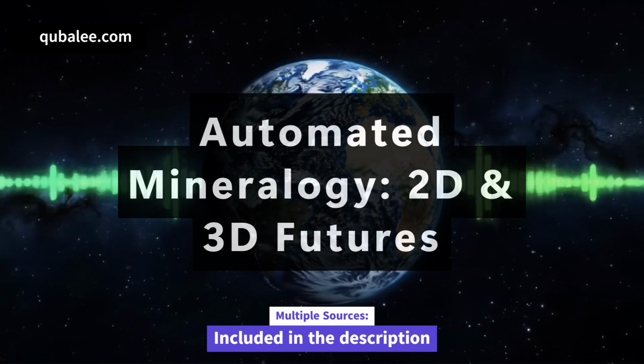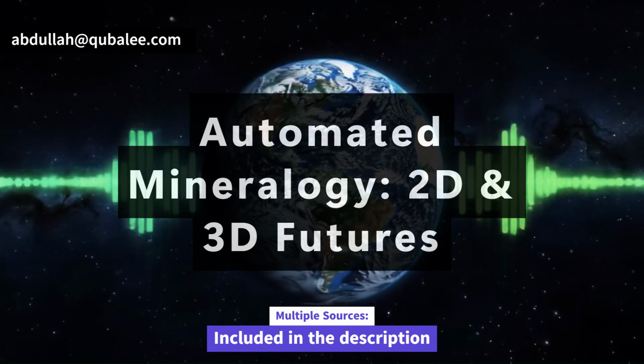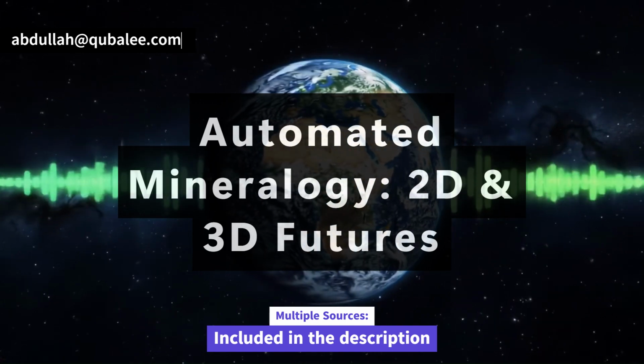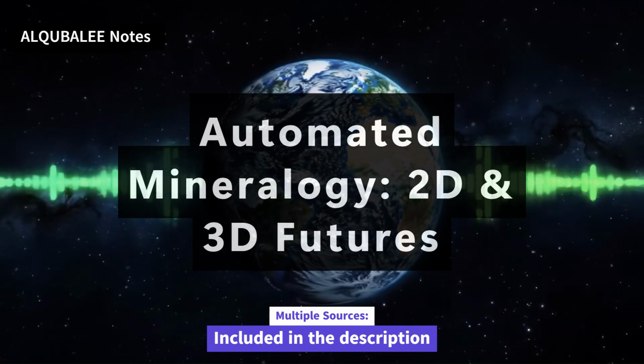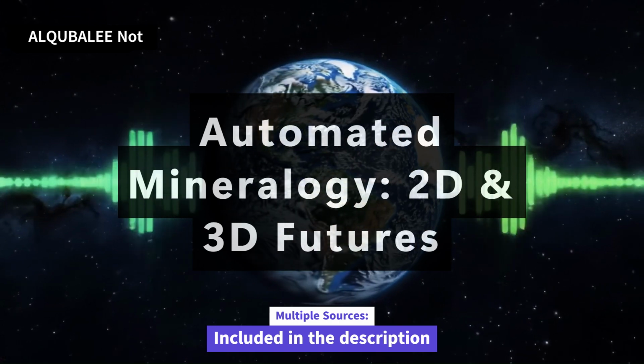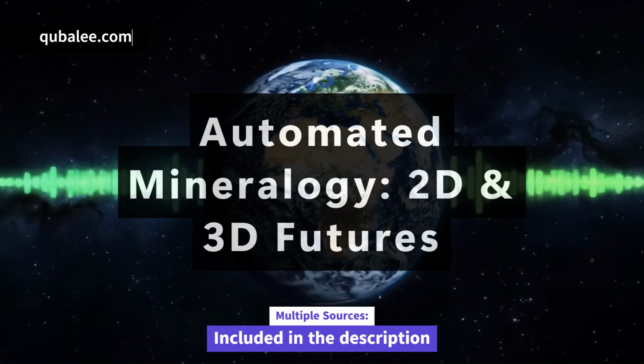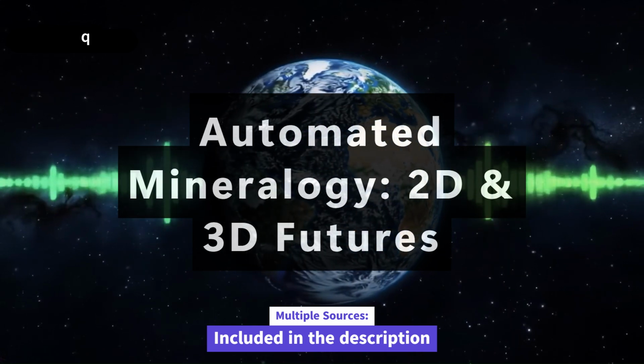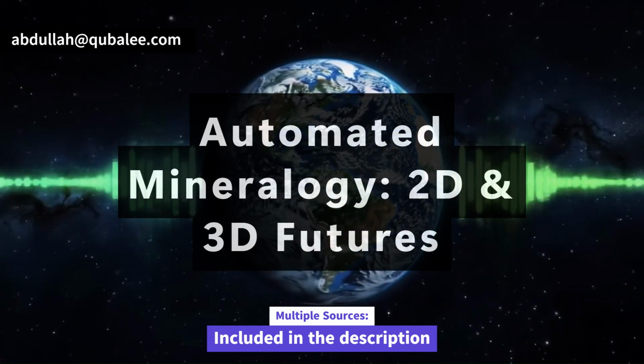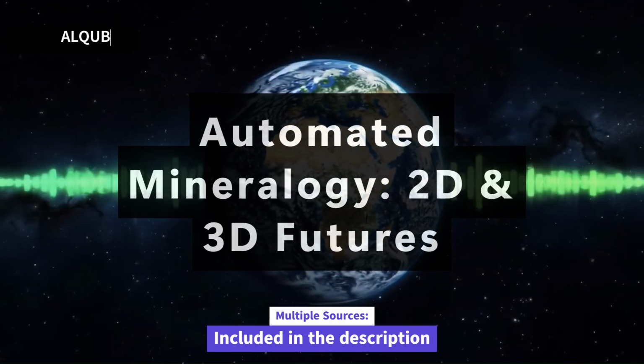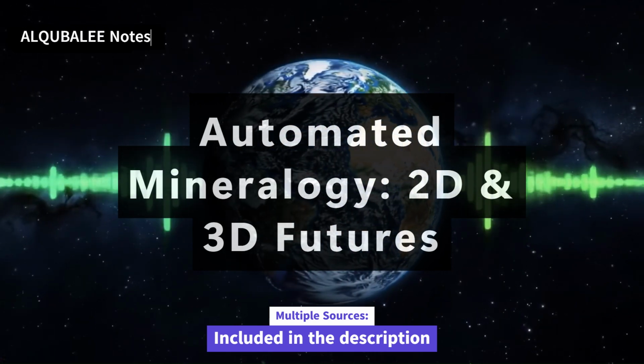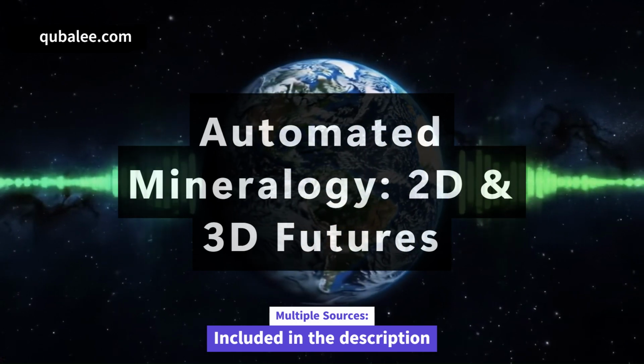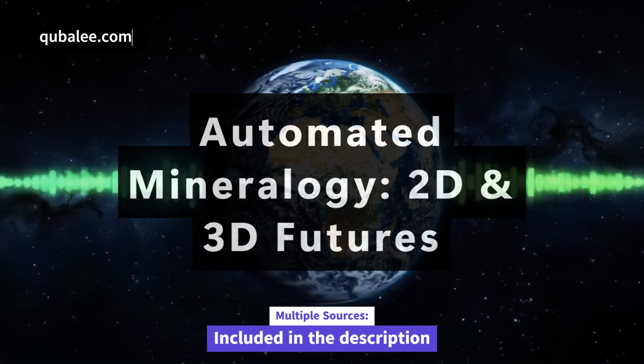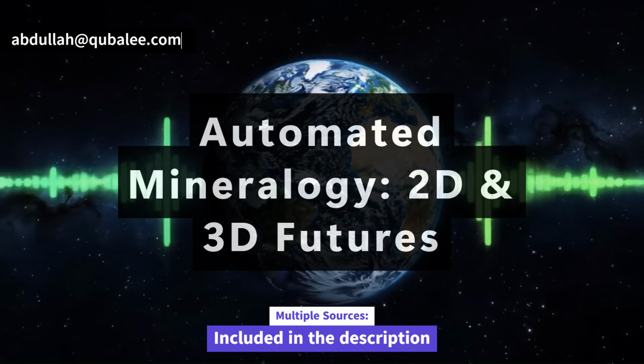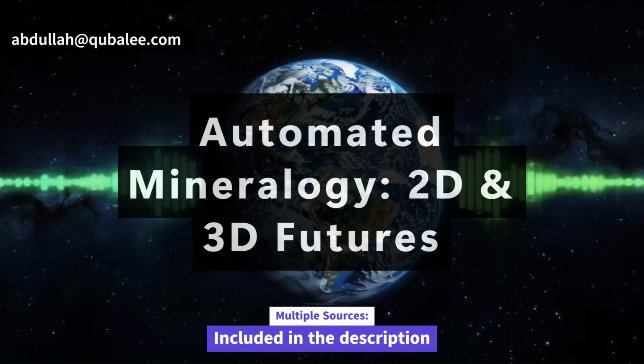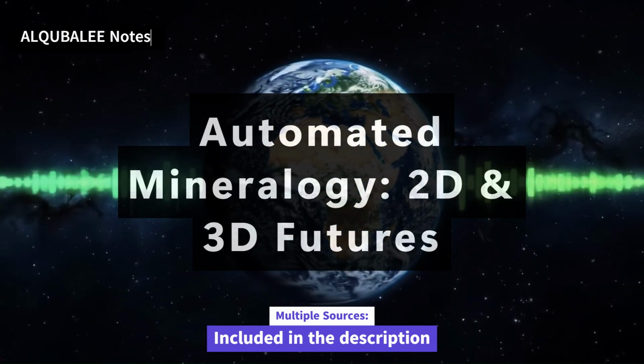You can digitally group together all the spectra from all the pixels that the software identified as, say, pyrite. So you grab all the pyrite spectra. Yeah. And when you sum up maybe millions of counts from all those individual pyrite pixels, you dramatically improve the signal-to-noise ratio. You're averaging out the random noise. And less noise means better accuracy. Much better accuracy for quantitative elemental analysis. You can then calculate the precise concentrations of the major elements in that pyrite, like iron and sulfur, but also the minor elements, much more reliably than from a single pixel spectrum.